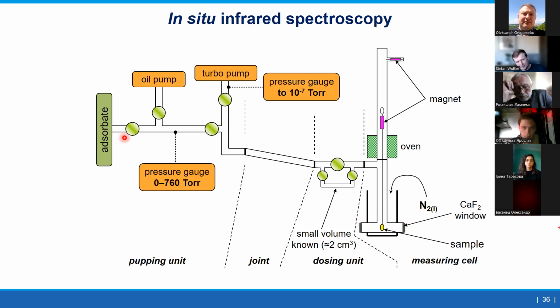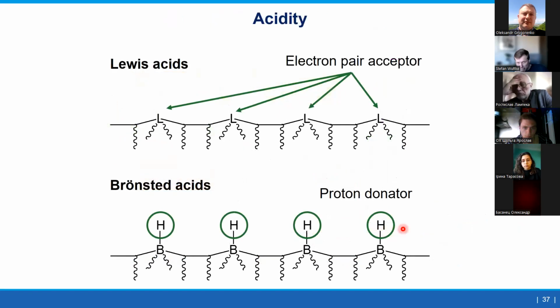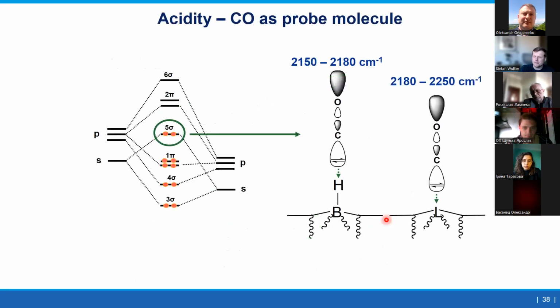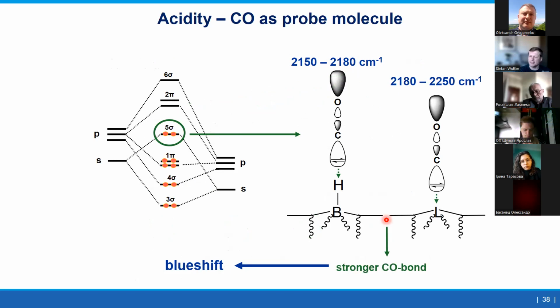And the idea is that you adsorb a probe molecule, in a very known amount, onto your sample. And you would like to measure acidity, for example. Acidity is very important, and you have Lewis and Bronsted acidity. Lewis acidity: things that like to accept an electron pair. Bronsted acidity is proton donor acidity. And you just want to measure it, you want to know how much there is and how. So I told you already, with CO. CO is a very nice probe molecule, and the HOMO, the highest occupied molecular orbital of CO, is a slightly antibonding orbital. Meaning, if you remove electron density from this probe molecule, you strengthen the bond. And when you strengthen the bond, you will see a blue shift in the IR spectrum.